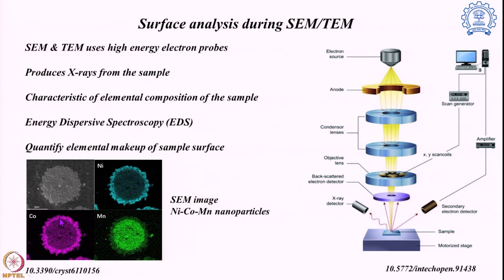Then you look into the cobalt through this violet color, you can see again most of it is present on the edge. But in the middle also they have quite an amount of presence, which is much higher than the nickel itself. Then the manganese, you can say it is mostly concentrated in the central area, in the core area. It is not much present on the shell area. So by that we can not only find out the shape of the system by SEM, and through the EDS study we can find out which of the elements are present, what is their quantity, and what is their overall spatial distribution. So that is why SEM-TEM coming with EDS actually is a nice tool to find out what is the behavior of different nanomaterials.